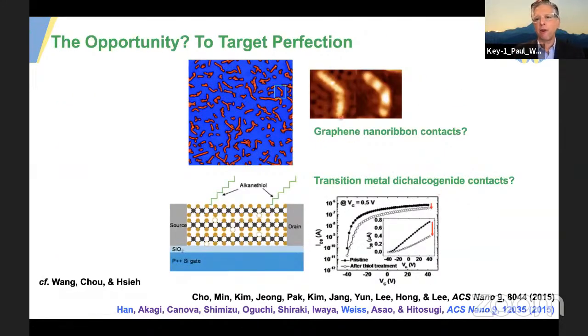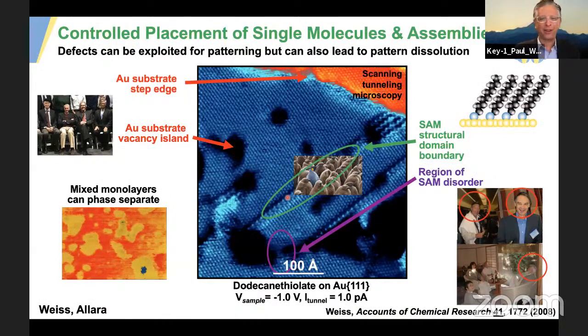And so, for instance, here's a graphene nanoribbon in which we map the molecular orbitals. We'll get to that. And seeing these nodes shows us that this would make a very bad contact. More on that later. In transition metal chalcogenides, Taeyoung Lee at Seoul National University did the following functionalization experiment. He filled in vacancies in molybdenum disulfide with alkane thiols so as to passivate the material and improve the electronic properties. So we would suggest taking this a step further and making these molecular connectors into contacts. And we learn to optimize the transport and the charge distribution through the contacts. And I'll show you how we're trying to do that. And emphasis on the trying to do that, rather than having already done that.